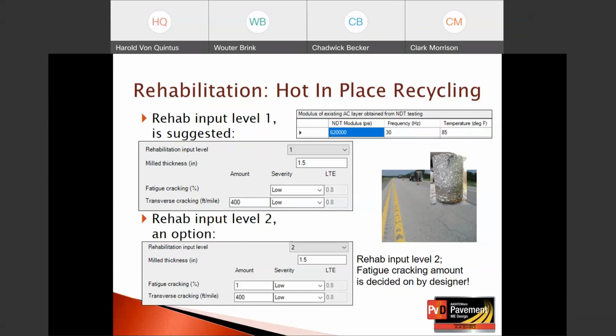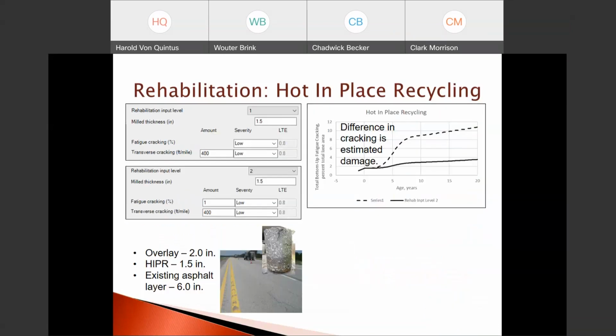But the transverse cracking is the same at 400 feet per mile, and we have a mill thickness for level 2. For rehab input level 2, the fatigue cracking amount is decided on by the designer. That's a decision the designer has to make. As noted previously, it would be a suggested value that whatever bottom fatigue cracking, wheel path cracking we see at the surface, if we do not have cores to confirm that that's top down and or bottom up, and we don't have deflection testing, then we would enter the amount of fatigue cracking based on the amount of cracking observed at the surface of the pavement prior to hot in place recycling strategy. So this now shows the difference.